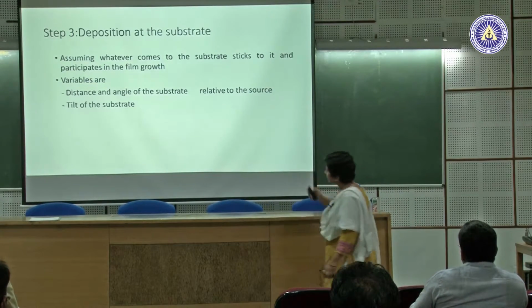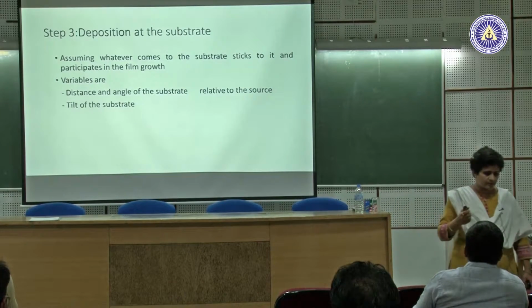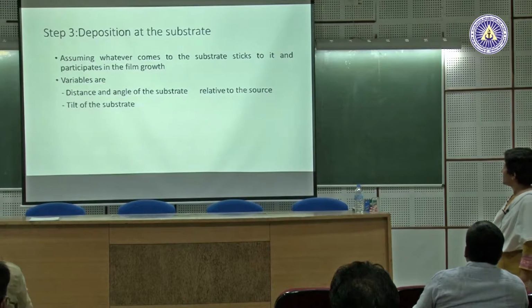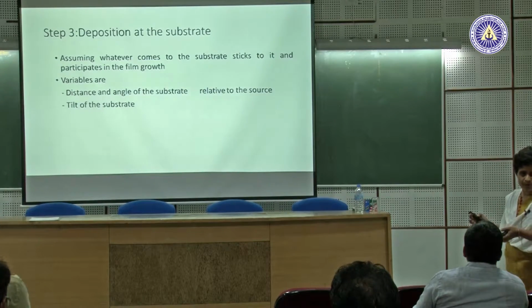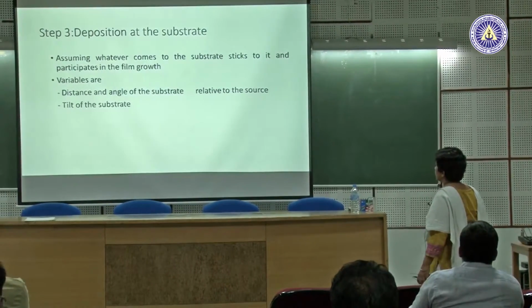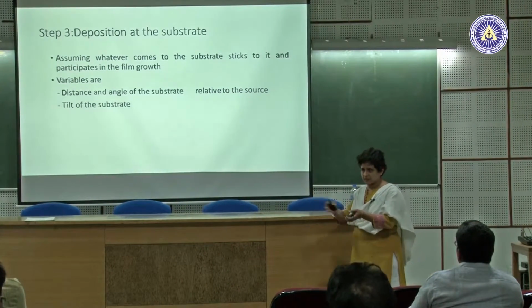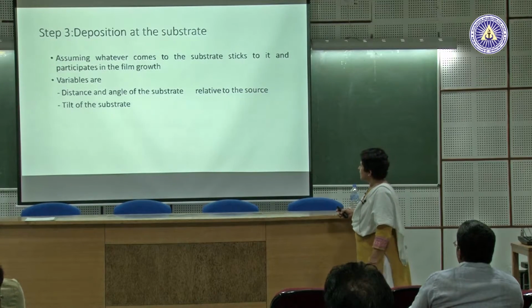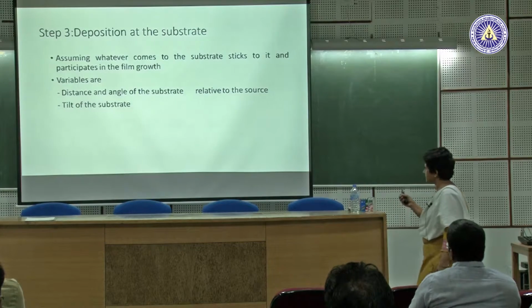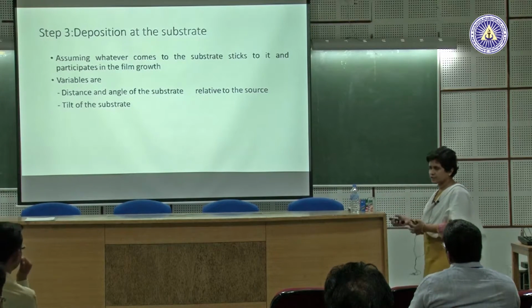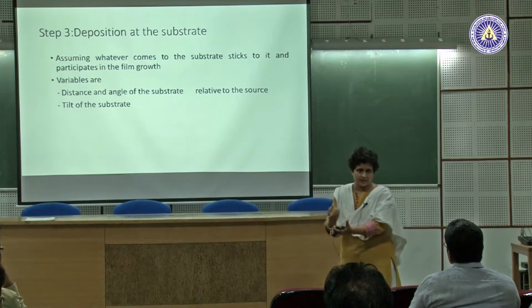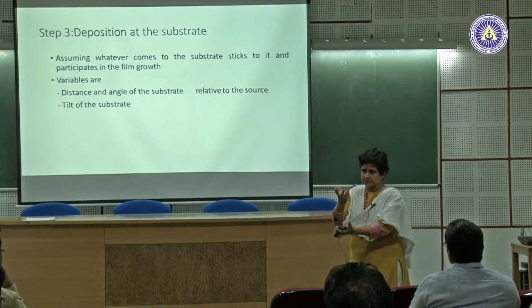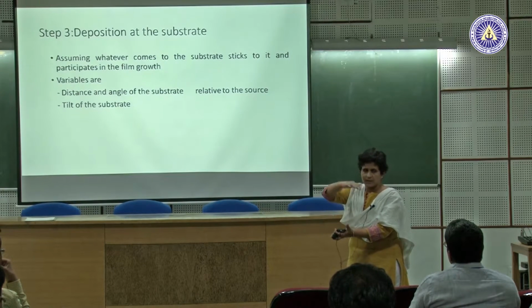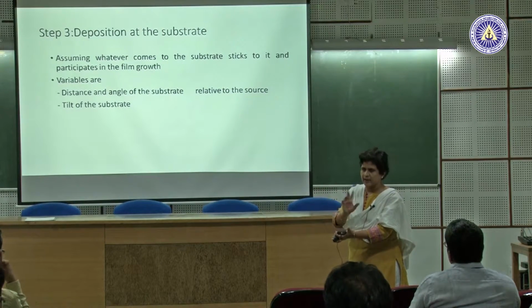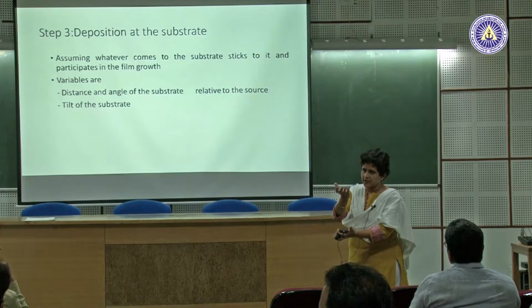Okay, so now this is another thing which again goes back to the physics and science of the thin film. Assume whatever you have evaporated is coming to your substrate. You can assume that whatever comes to the substrate either sticks to it and participates in the formation of the film. The variables are distance and angle of the substrate related to the source, and tilt of the substrate. You can calculate, because there is going to be a geometric factor on how much of the evaporated material is coming to the substrate. So there will be a geometrical factor on it too, but let us say you can calculate that and you will assume that so much of it is coming on the surface, either all of it is deposited or none of it is deposited, right.